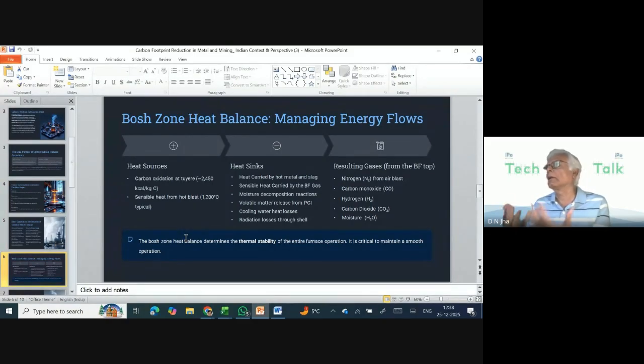So the carbon that you are burning is generating heat. In the Bosh zone, please do remember that hydrogen is not getting oxidized. It is remaining as hydrogen, so it is not generating any heat in the Bosh zone. Is that clear? The heat is generated at the bottom, and the reduction is happening above the cohesive zone.